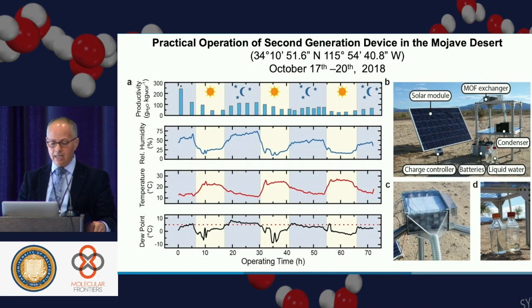get higher yield. And this was taken by my students in the Mojave Desert. And you see here the humidity measured during the experiment. It rises during this time in October, it rises up to over 50%, but also it goes down during the day as low as almost 7% relative humidity. And the students can still harvest water day and night. Ignore this first column. That's the water that was in the MOF from Berkeley. That's Berkeley water. But this is Mojave Desert water.